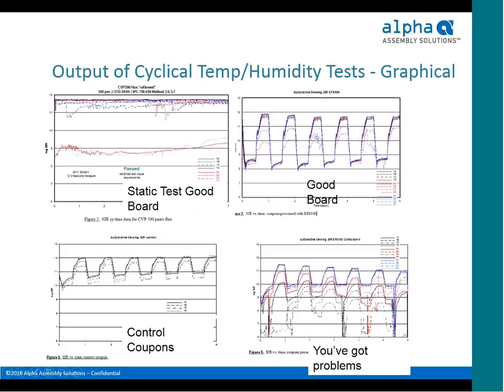And then here is the SIR output. So unlike the top left, which we saw earlier, which was our static J standard 004B test at static conditions, the rest of these all show what happens when you actually cycle the temperature and humidity. Temperature and humidity can affect the resistance of materials and the conductivity of the environment, and so you'll see reflected that in the measurement, you'll see the cycles as they occur. So on the bottom left are control coupons. Those show the effect on just a bare board with no materials attached. The top right shows a good board where you see the cycles, but you see consistent performance. You don't see any of the resistance values dropping too low.